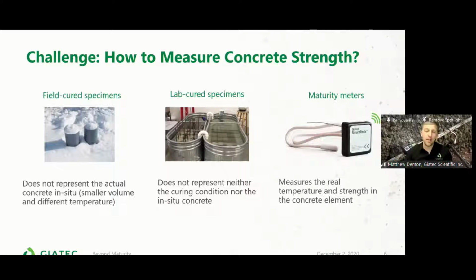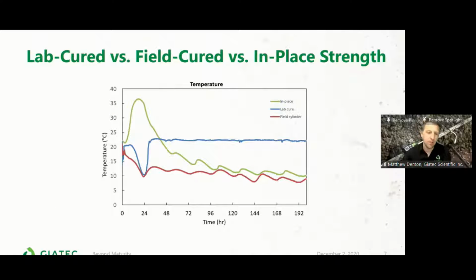And then the third method, which is a growing trend, is the maturity method. That's when we measure the real-time temperature on a continuous basis to determine the strength. So let's have a look at where this method comes from very briefly. When we look at this graph, you'll see that there's a big difference between the temperature of the concrete placed on site versus your lab cured sample versus your field cured sample.